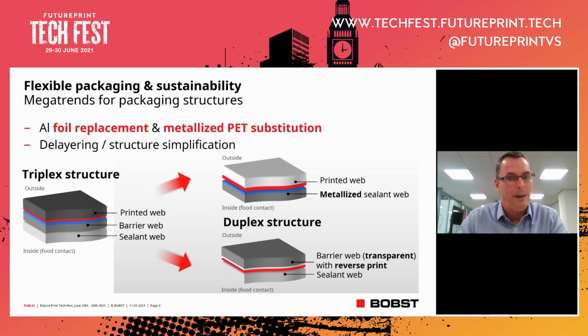If we want to simplify the structure from the triplex 3-layer to a simplified 2-layer bilaminate or duplex structure, we have a few options on how to design the packaging structure to combine these functional properties. For the example shown on the upper right-hand side of the slide, as the barrier layer is aluminium, it is opaque, and therefore we can't reverse print behind an opaque layer. So for the example on the upper right-hand side, we have to put the opaque metallized layer on the sealant web, and therefore combining the functional properties of barrier and sealant on the same web.